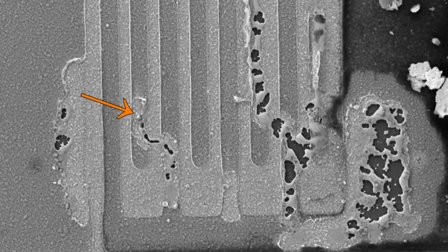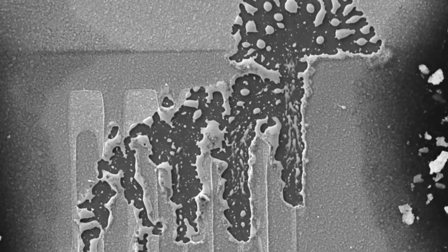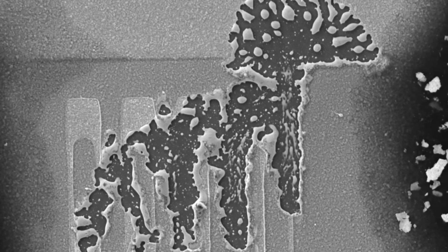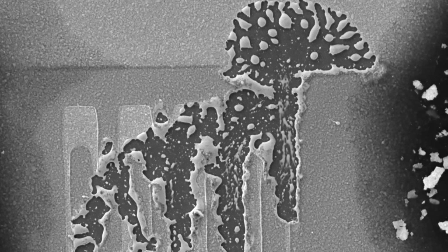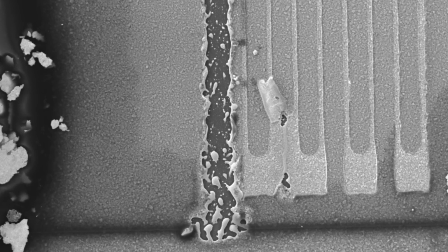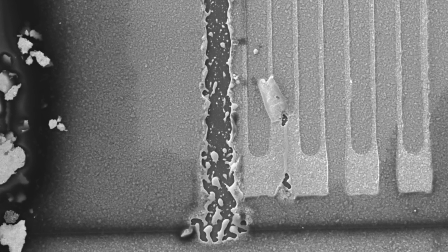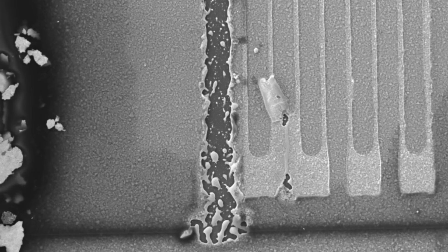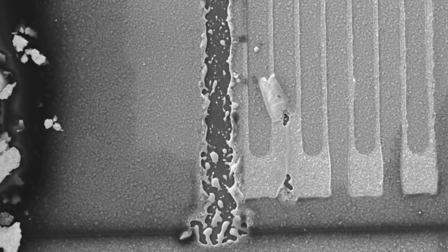You can trace the exact path the short circuit took, from one electrode to the other, leaving behind molten bits of material. I think the oxide was probably heated up rapidly due to internal resistance, and then reaches a critical point where the temperature is hot enough to melt it. This allows more current to flow, propagating the effect, resulting in, basically, a molten short circuit.